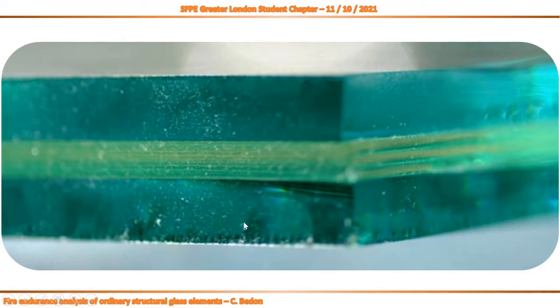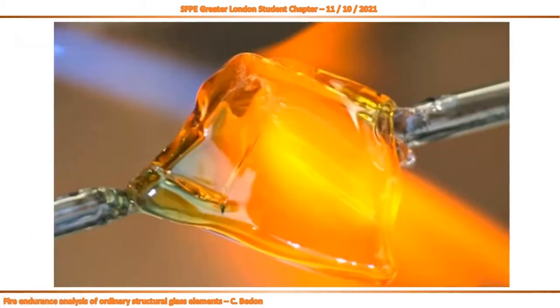In most cases, you will need to take care of glass elements that are characterized by large dimensions but a very small thickness. So something that will represent the critical aspect for design considerations. For sure, you can bond together 2 or more glass layers. We can talk about 3, 4, or even 5 glass layers in a laminated section. But in any case, this thickness will most probably be very small compared to the total size. So why are fire considerations and fire resistance discussion important for this brittle-in-tension material? It is very important because of the intrinsic material properties.